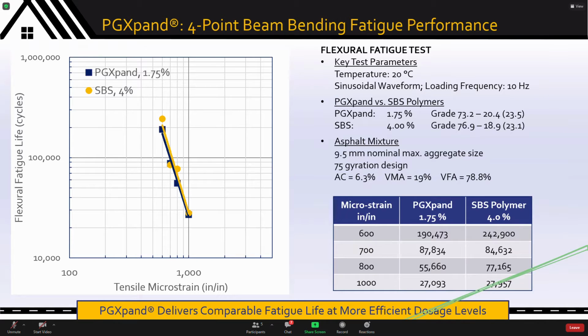Here is the fatigue performance. Again, this is a 4-point beam bending fatigue, 20 degrees C, 10 hertz loading. 2 mix examples, one with 1.75% PGXpand and one with 4% of SBS, roughly to get to the same high temperature grade. And you'll notice that the PGXpand sample is able to maintain the low temperature properties a little bit better. As a function of different microstrain loading, you can see that the fatigue resistance of PGXpand mixes is truly excellent.